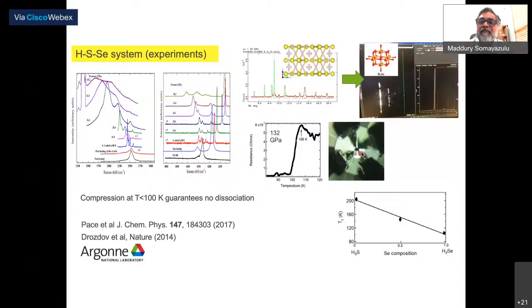This is a typical way we measure. What you see here, this bright circle, is the culet of the diamond anvil, about 100 microns. And the sample, in this case a selenium hydrogen sample, in fact work done by one of your colleagues, Ajay Mishra from PARC, is encased between 4 electrodes on which we can do van der Pauw measurements and electrical conductivity measurements in a cryostat. And this sample size is of the order of about 30-40 microns. We can get great diffraction from HPCAT on a synchrotron beamline and actually evaluate what the structure looks like. And so we know, for example, we can do a refinement of the occupancy of sulfur and selenium.